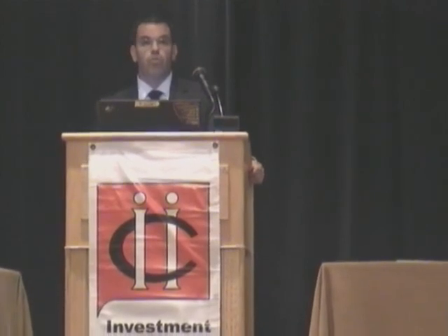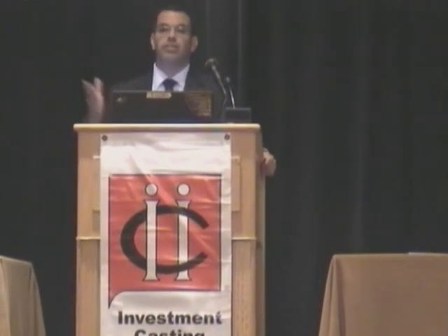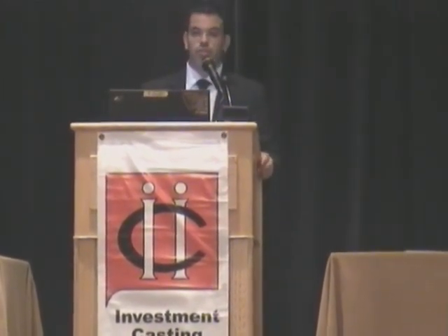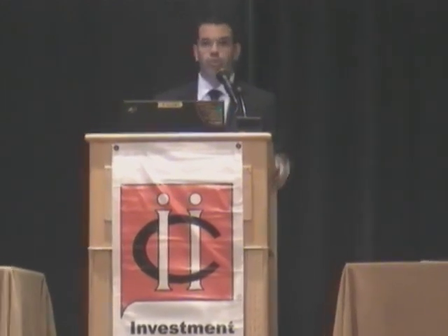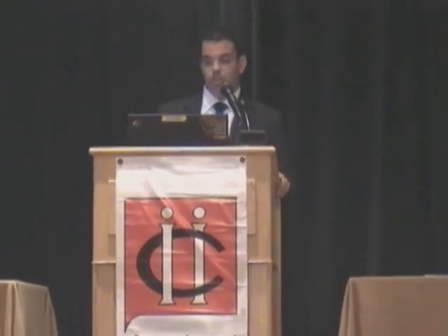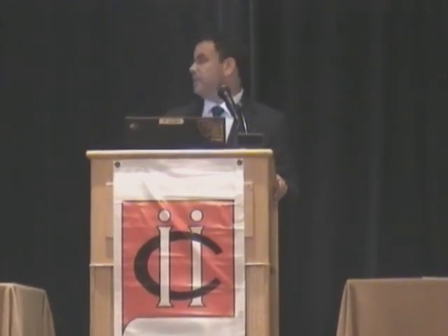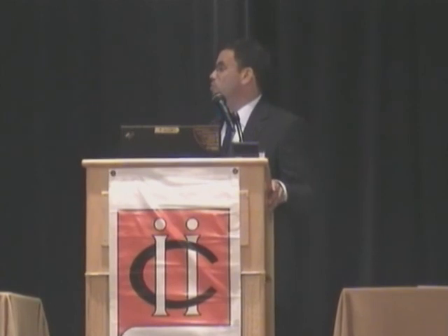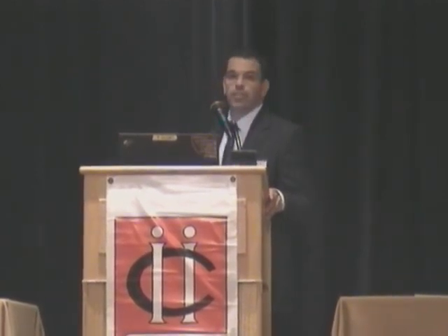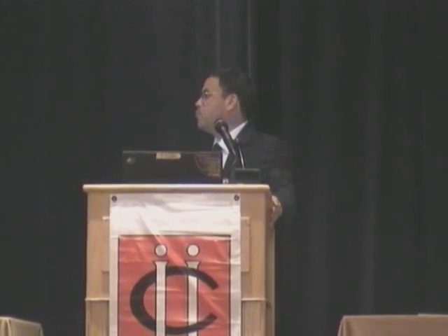High rate of part defects without understanding the root cause, or let's say understanding the practical side of the root cause, led us to very weird assemblies with weird parts on them. Some of the examples, you can see 17 feed gates on the left picture. On another small part, you can see on the right side more than 6 feed gates on a very, very small valve, 4 parts per assembly. I won't tell you the amount of scrap because I don't want to embarrass myself, but 4 parts per assembly and 7 feed gates.